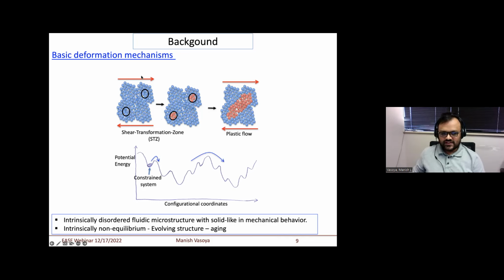This is the initial configuration before loading. Once you impose a shear stress, you can see that in some places those atoms rearrange themselves and induce a local inelastic deformation, and there can be many of them. If you keep increasing the loading, those local inelastic deformations can form a shear band, or localize and induce large deformation. When an individual STZ happens, the system goes from one local minimum to another local minimum, step by step.